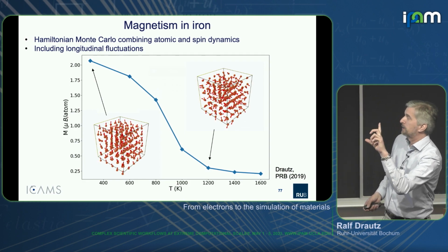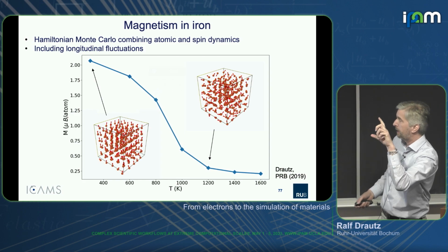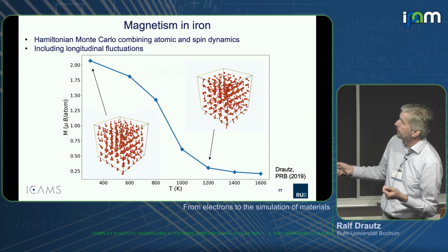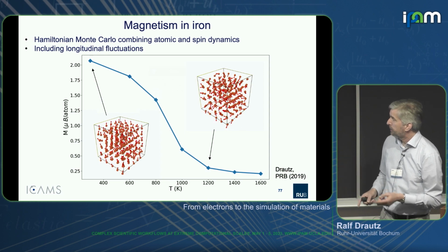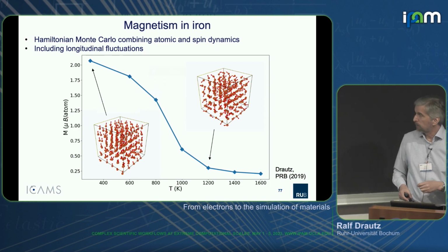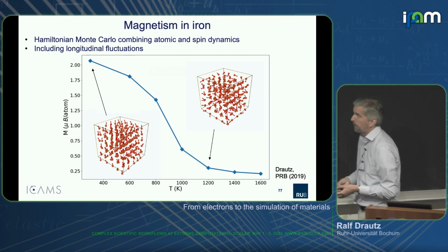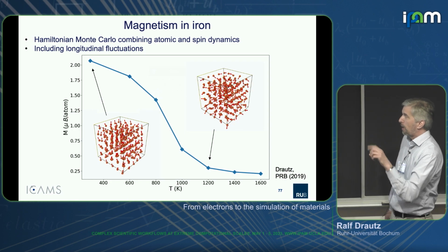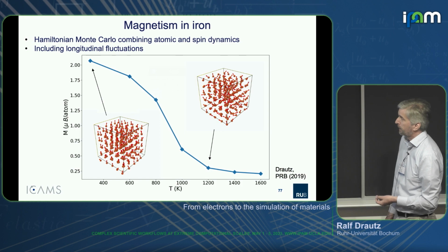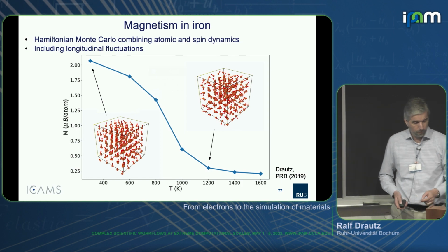and every atom carries a magnetic moment that can rotate and that it can change its magnitude. We have ferromagnetic here, all aligned in parallel, and at high temperature, they point in all kind of random directions. And so we are paramagnetic. But the important thing is the prediction is in agreement with the experiment, the magnetic moments do not collapse. It's really a paramagnetic state that is predicted.